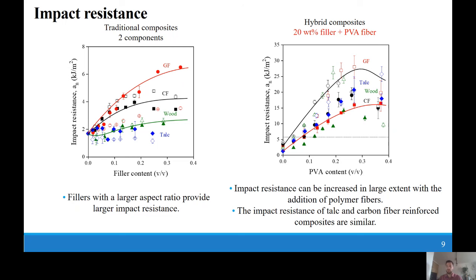only 15% PVA fiber. The largest impact resistance was achieved without the use of coupling agent in the case of glass fiber reinforced hybrid composites, which was 30 kilojoule per square meter. This value is already very favorable for the industry. It's worth again drawing the attention to the fact that talc PVA composites have a similar impact resistance as carbon fiber reinforced PVA hybrid composites. It is important because the price of the fillers is very different.